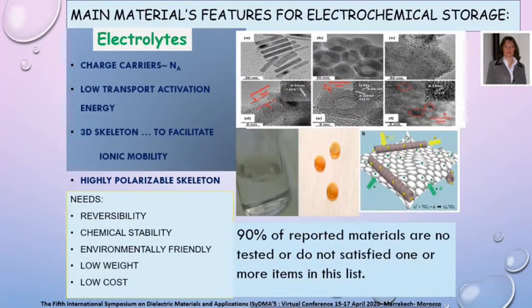To find a good material to use as electrolyte, it's necessary to satisfy a list of requirements, like a large amount of mobile carriers with a low activation energy in a highly polarizable skeleton. Also, it is needed a material with chemical stability, lightweight, low cost, cheap, and friendly with the environment. However, almost 90% of the reported potential materials have never been tested in real batteries, and they don't satisfy one or more than one properties in this list.